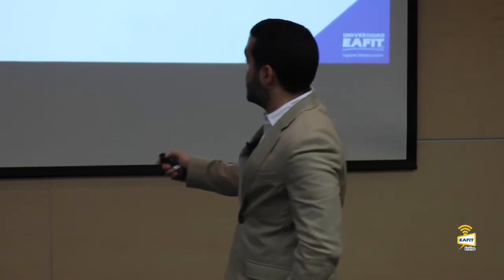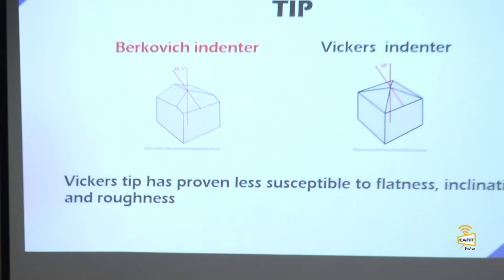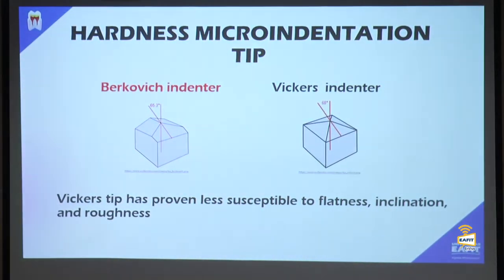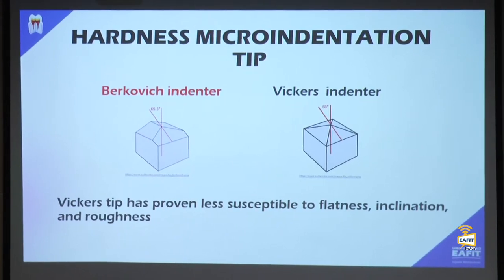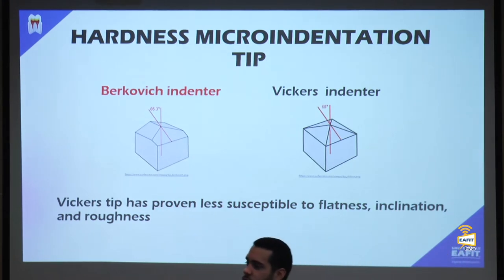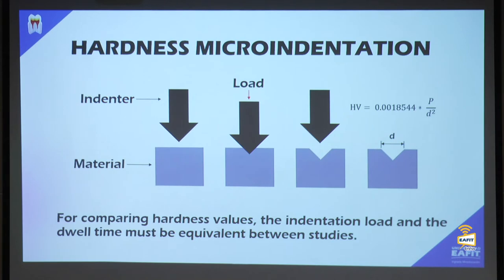There are two standard indenters for our procedures: the Berkovich (three-sided pyramid) and the Vickers (four-sided pyramid), both typically made of diamond. We used the Vickers tip because it's less sensitive to surface roughness, flatness, and inclination of the layers — which helps shield the measurement procedure.